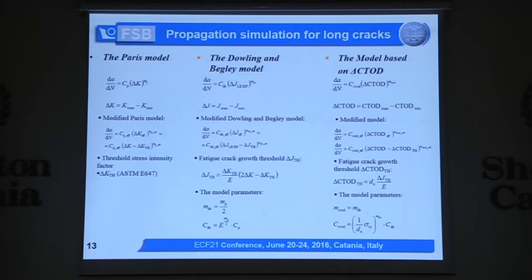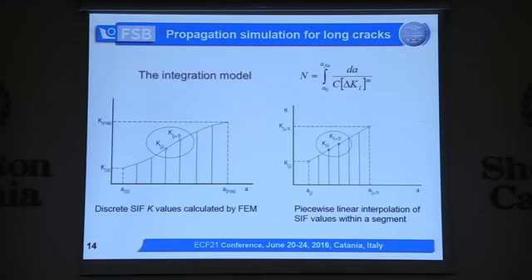And we started with Paris equation, but today we have like 8 different power law models and even more. So I just mentioned some of them because we use another two which you will see later. And I want to mention that we integrate the fatigue crack growth life by using numerical simulation procedure developed in MATLAB, and we have piecewise distribution between discrete points, and then we also integrate this numerically to get fatigue number of cycles.